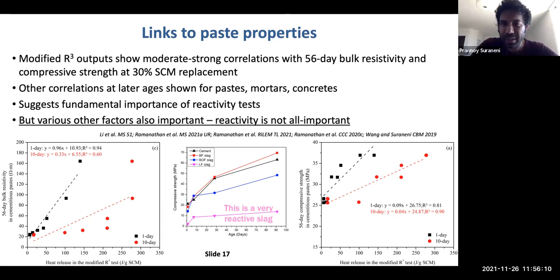So you can make these relationships, but just don't look at a 1:1 relationship and go, oh, this is fantastic, I can always use the reactivity to predict strength. It's not as simple as that. Strength or bulk resistivity, for example, are commonly affected by other properties as well. But you can, of course, use the reactivity as a starting point or for screening.